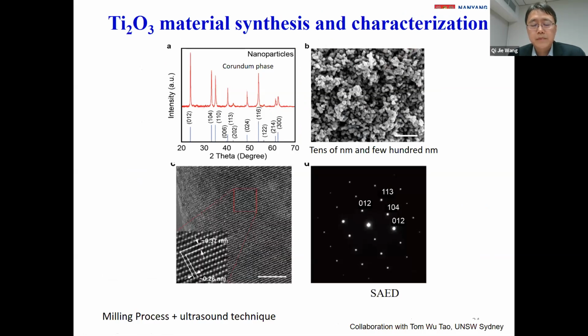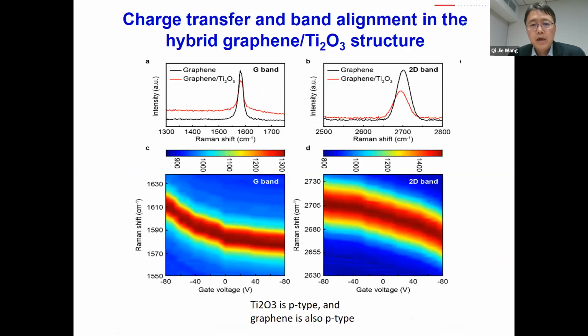We worked with Professor Tom's group from Sydney to get the high quality material. And for such structure, one important part of the device is the carrier transfer from the nanoparticle to graphene. So unfortunately, the as-grown Ti2O3 particle and the graphene are both p-type material. So that's why, based on this Raman peak observation, you don't see their shift, meaning there's literally no efficient carrier transfer from nanoparticle to graphene in as-grown samples.